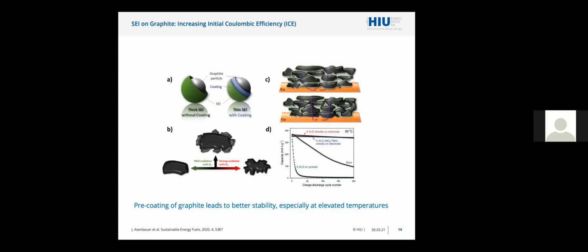One of them has been, for example, to pre-coat an artificial SEI on graphite in order to limit as much as possible the consumption of charge during the SEI formation. And you see here that pre-coating of graphite actually can lead to better stability. You can also use materials for this pre-coating which are stable at high temperature, and this would then result in better performance of the graphite electrode at high temperature.